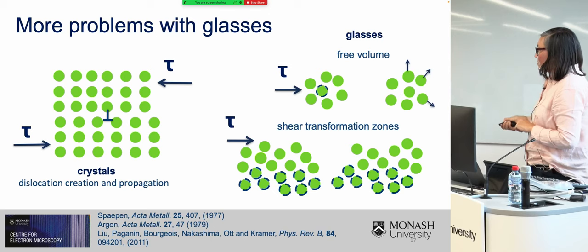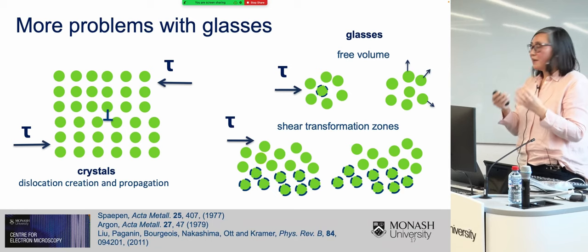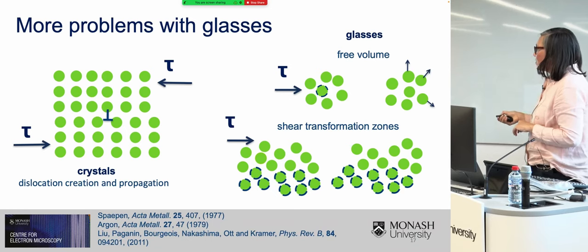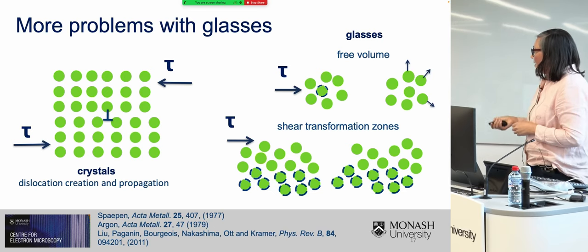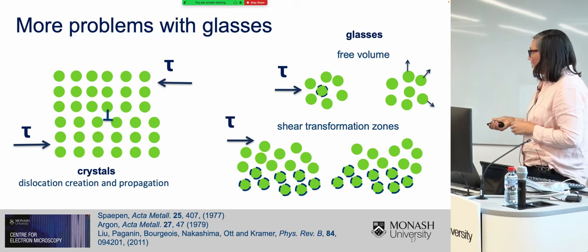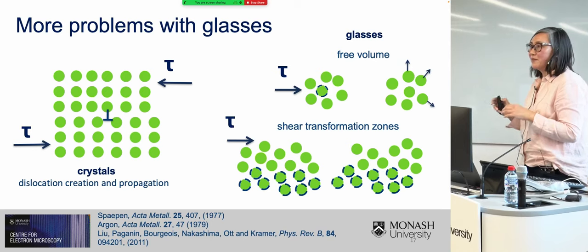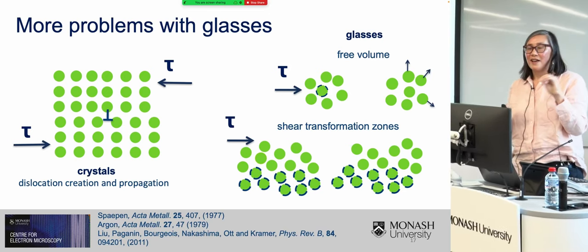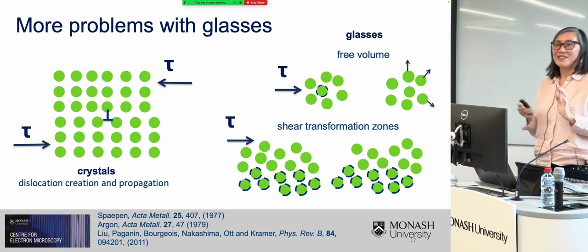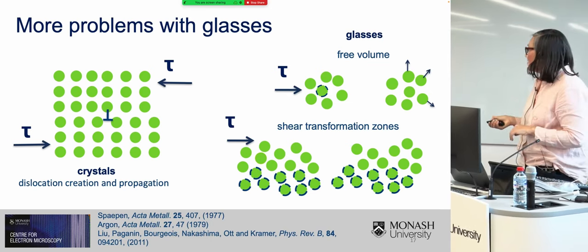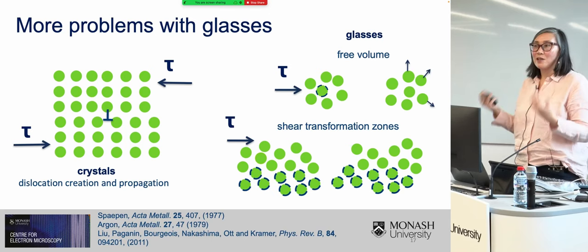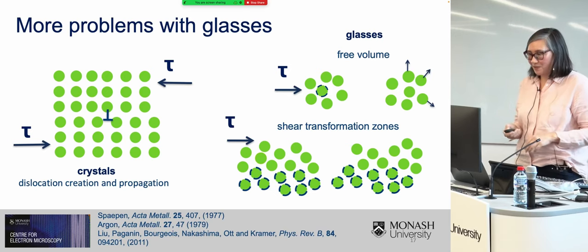So here are two ideas that have been suggested in the past. This is the creation and diffusion of free volume, and also the transformation of these zones that are somehow sort of structurally soft. However, the size of these zones and the nature of these zones is still quite unknown. And here I'm just citing an early investigation I did with David Paganin, where we actually looked for pockets of free volume that had condensed into nano-sized voids, and we found none. And so we reported a null result. And I just wanted to highlight this because sometimes null results actually put you on a better research path.